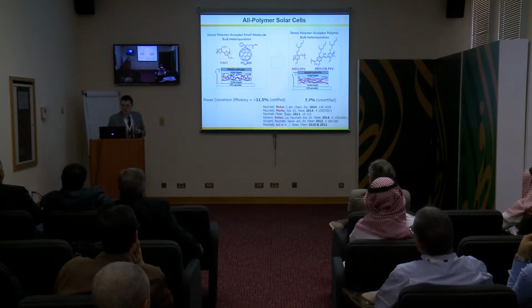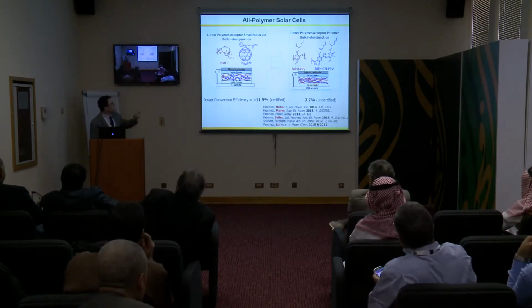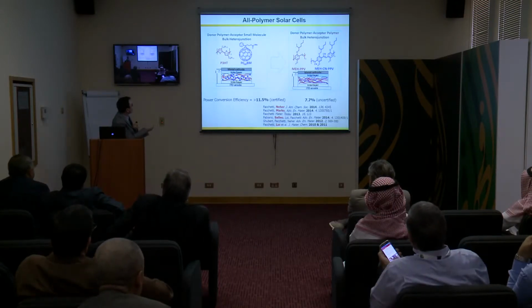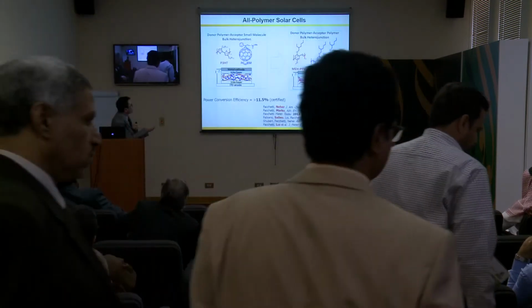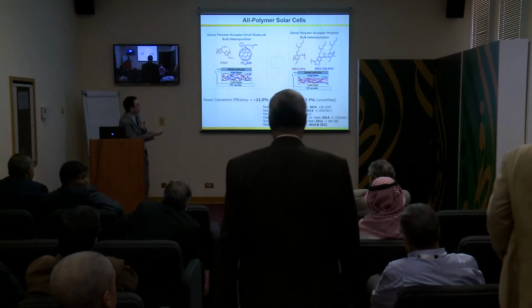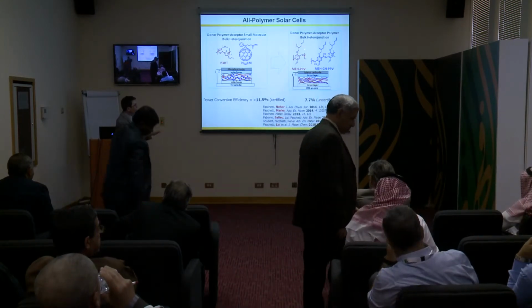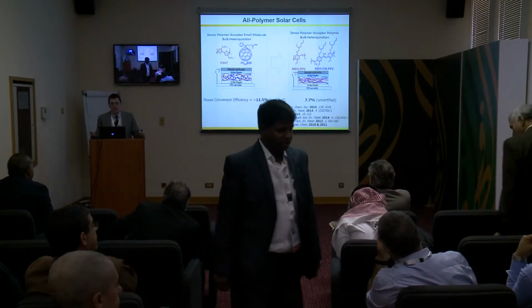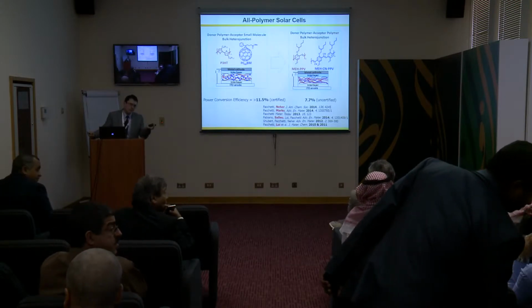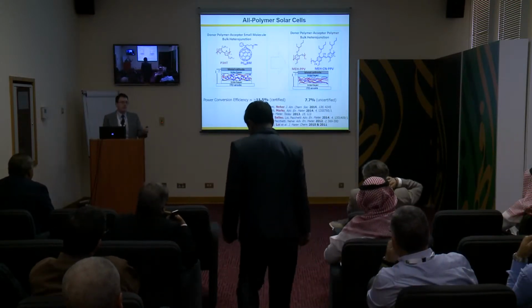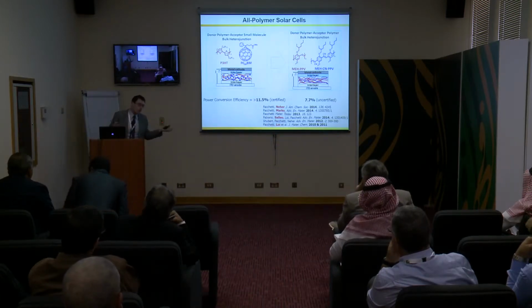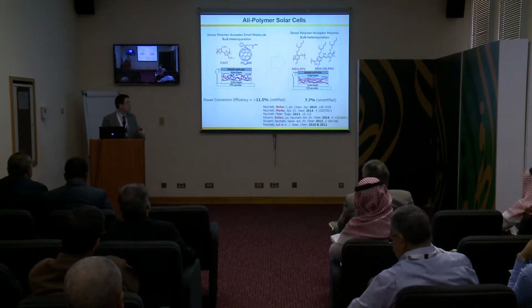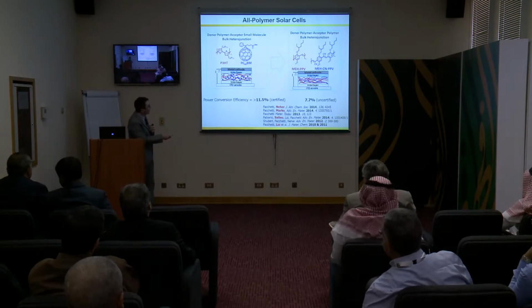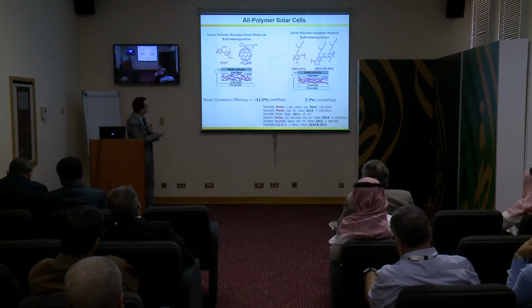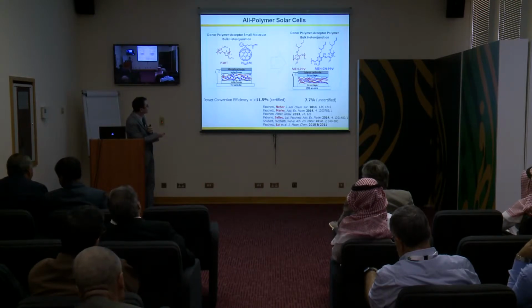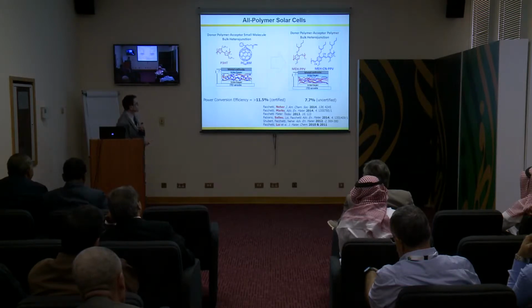Okay. For the very last few minutes, I want to talk about one of the works we have done more recently, which is really trying to move away from P3HT or donor-acceptor blends based on a fullerene, and instead using a blend where both the donor and the acceptor are polymeric. This remains challenging, though not from the theoretical point of view. There is really no difference. Why should this blend not work as well as fullerene? There is really nothing fundamentally different. But the real key problem is to achieve a morphology which is comparable in terms of domain size and domain purity to the polymer-fullerene type of cell.